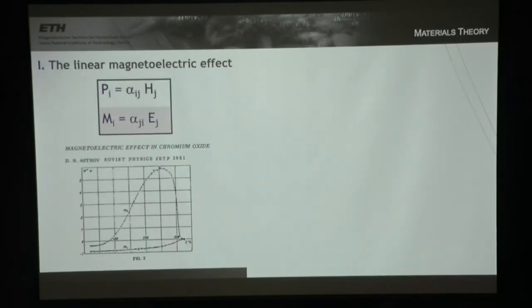Okay. Here's the data. So this effect was predicted in chromium oxide (Cr2O3) in 1959 by Dzyaloshinskii and measured a year later by Astrov. He didn't label his axes. This is the magnetoelectric response in some units that he didn't state. Oh, he has labeled this one. Here's the temperature. This is the magnetoelectric response as a function of temperature parallel to the axis of the chromium oxide, and here it's perpendicular. And so you see that they're different and they're non-zero, and these are the non-zero components.